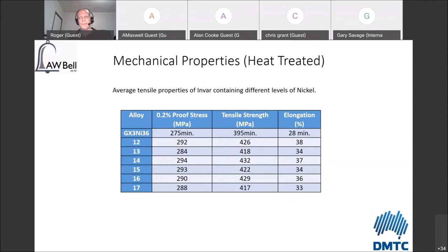Now, I know for those of us who work in aluminium, we're not always used to seeing very high elongations around 30 to 40%. But sure enough, if you can achieve these kinds of low strength values, you do get this sort of high elongation. And I would say if you plan on manufacturing Invar at all, the fact that it's got these tensile properties make cutting with abrasive wheels very, very tricky. It tends to glue up your abrasive wheels very, very quickly, and things get pretty warm pretty quickly.